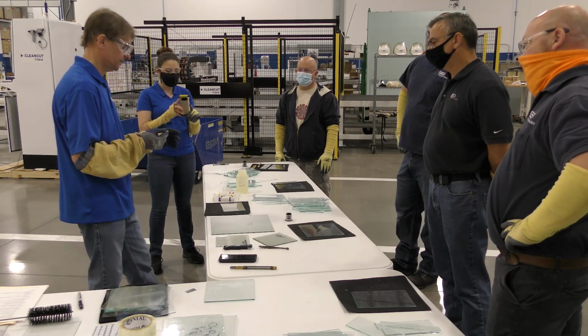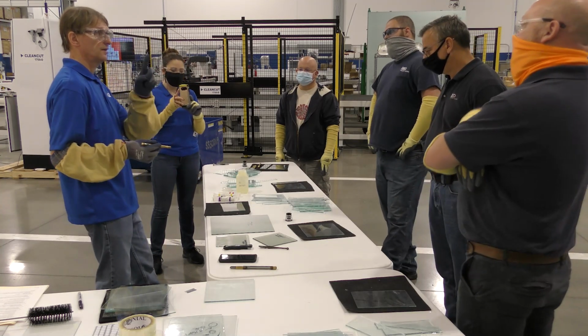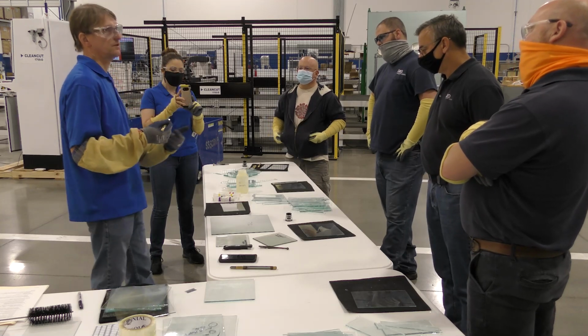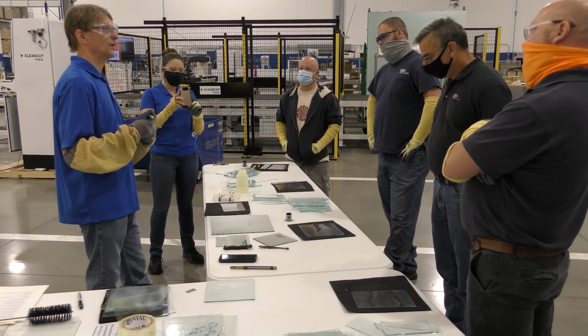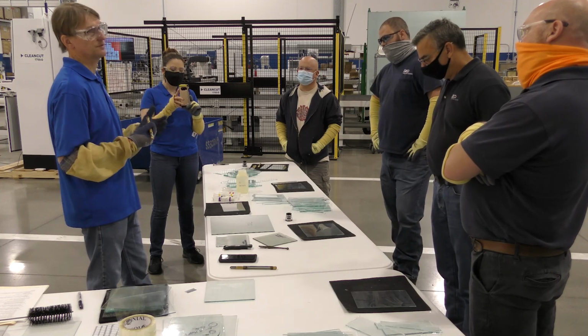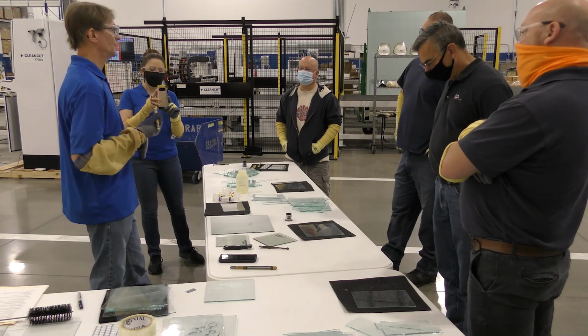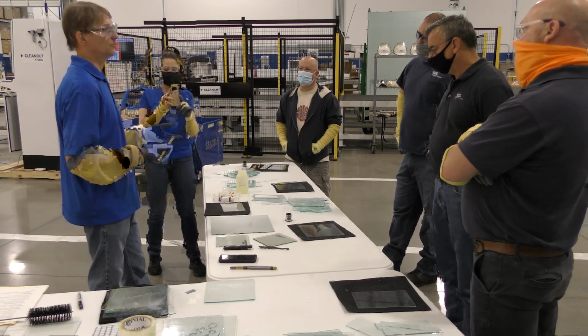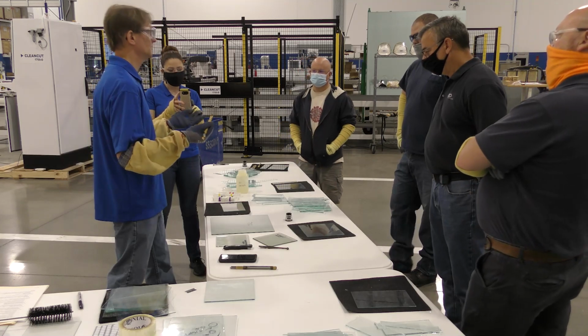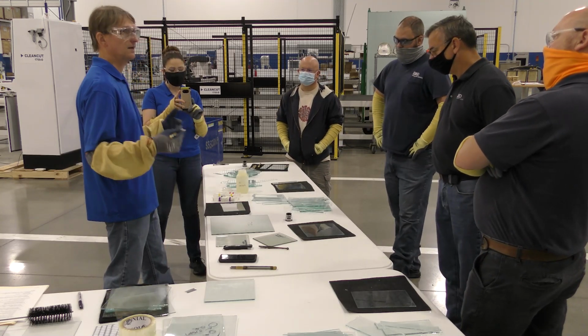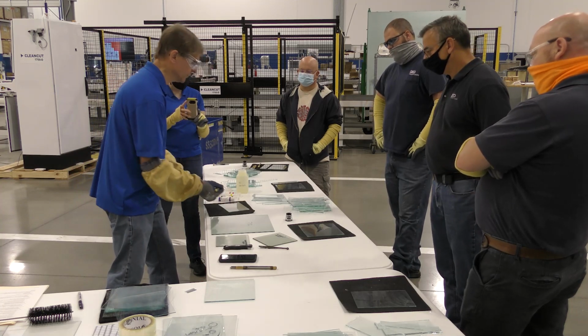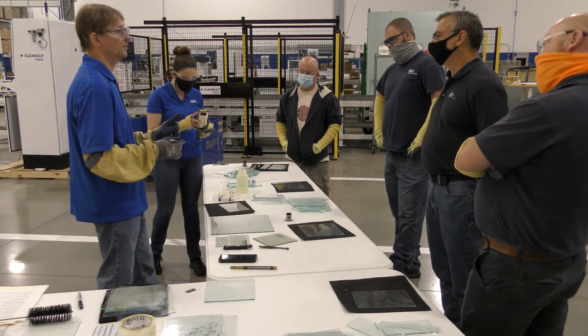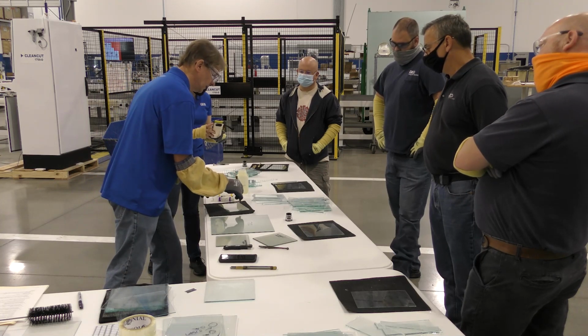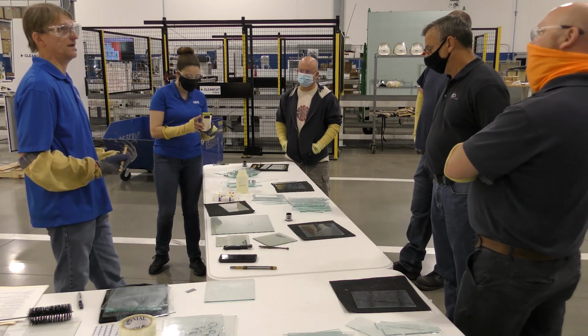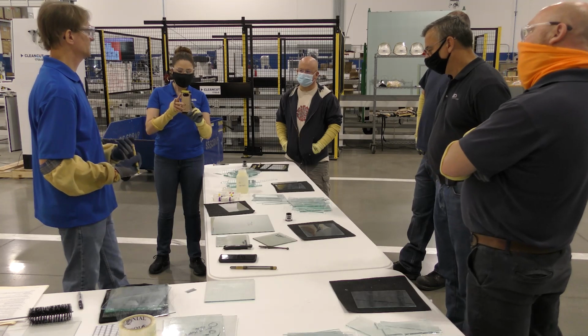Cutting fluid does two things, primarily. Number one, it lubricates the axle and the wheel, and it probably by a factor of 90+% increases the wheel life. If you're running dry, expect to change your wheels very frequently. So it basically is a lubrication for the mechanics of all the friction and everything that's going on. The second thing it does, most importantly, is it pushes cutting fluid into the fissure depth, into the fissure, and prevents the glass from healing.